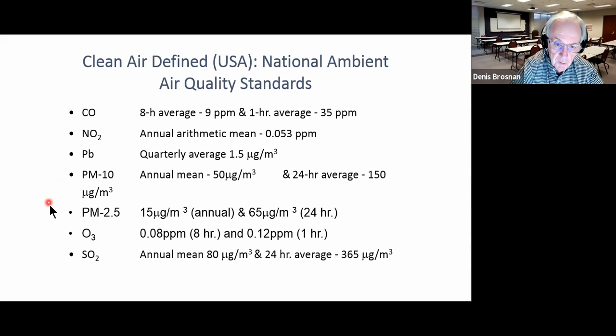Our regulatory people also define something called PM 2.5, 2.5 microns, and they consider those to be fine particles. Not me. I consider fine particles to be those that pass through a fabric filter, which means that they're usually about a micron in size. It turns out our regulatory people figured out that they could only measure particles as small as 2.5 microns with the equipment they had without spending a lot of money. So they said, okay, we're going to have a cutoff at 2.5 microns, not a micron.